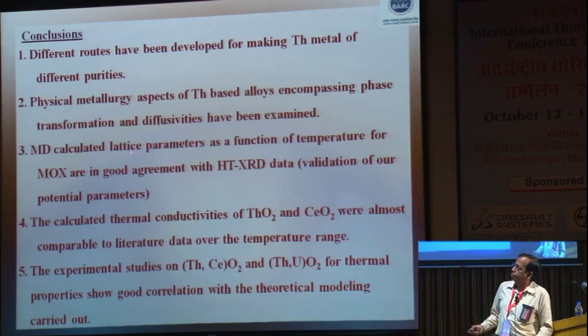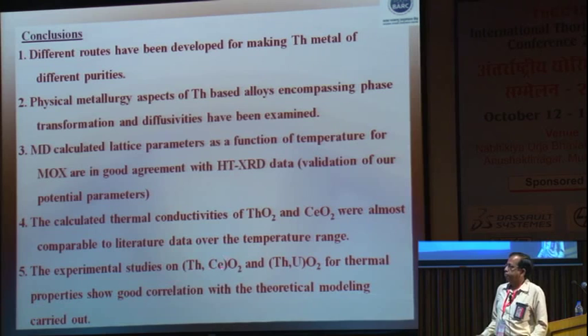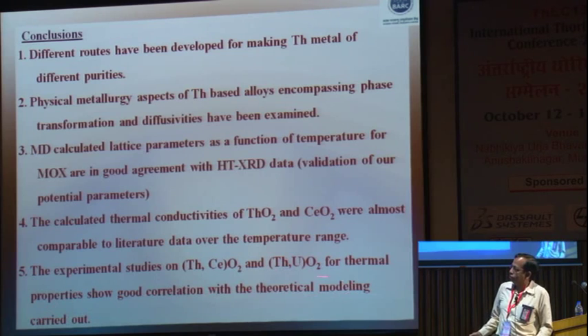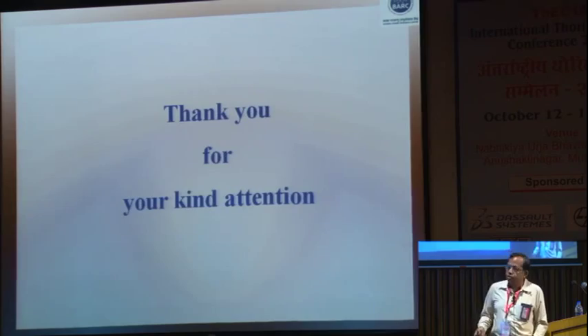MD calculated lattice parameters as a function of temperature for MOX are in good agreement with the HT-XRD data. The calculated thermal conductivities of ThO2 and CeO2 were almost comparable to literature data over the temperature range, and the experimental studies on (Th,Ce)O2 and (Th,U)O2 for thermal properties show good correlation with theoretical modeling that we have carried out. So with that, I come to the end of my talk, and thank you for your attention.